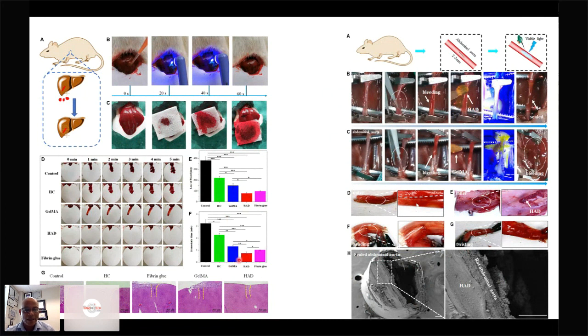And this is the time that it would take for the blood to form a clot. And then again, you can see that this is a very, very short time. Practically, what it means is that if someone is losing blood and you apply this gel, you can actually stop the bleeding within such a short period of time, and then you lose very little blood in the process. So not only did we try it with liver,